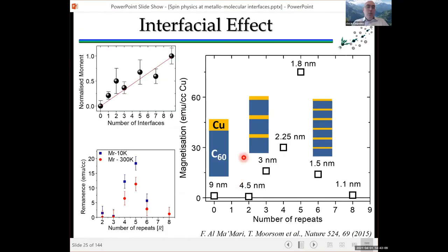We wanted to make sure that this was not due to impurities, as you can imagine. So what we did is grow the same samples, but changing the number of interfaces. So the same amount of copper, the same amount of C60, but broken down in different number of repeats. And we saw again that the magnetization only appears when the copper layers that we are splitting our total copper thickness into is between 1.5 and 3 nanometers.